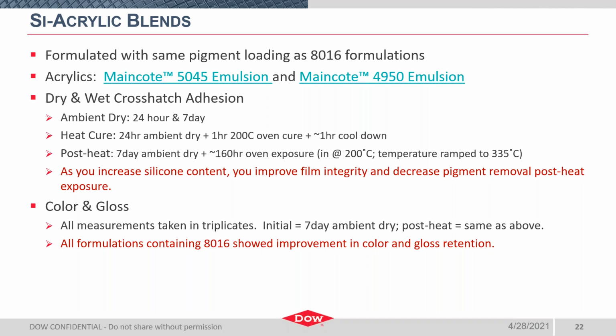Testing completed included dry and wet crosshatch adhesion after several curing or drying protocols, which encompass the traditional testing schematics for silicone and acrylic paints. These included adhesion after ambient cure or dry at 24 hours and at 7 days.